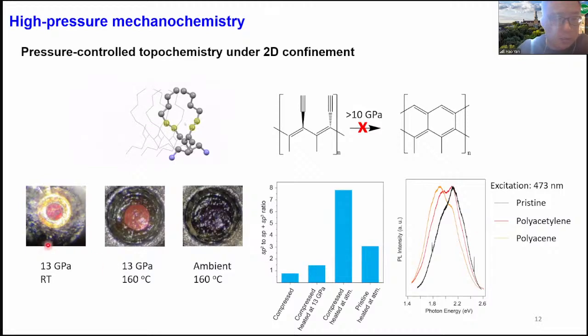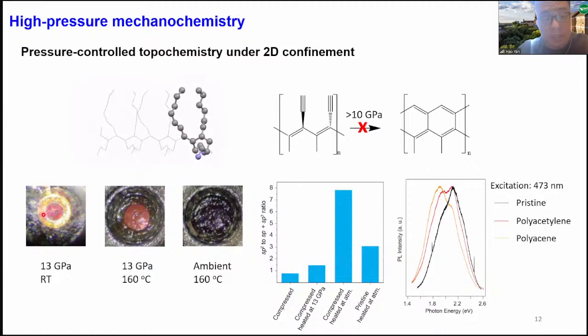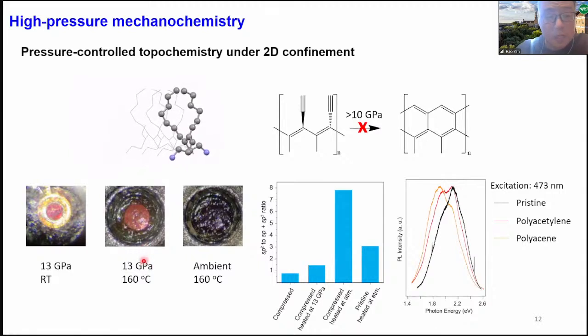You can see that very clearly from the color change. If I press it to 13 gigapascal at room temperature, I got my polyacetylene, and keeping that pressure and heating it up, nothing changed. If I release the pressure, then heat it, all of a sudden the polymer becomes black.